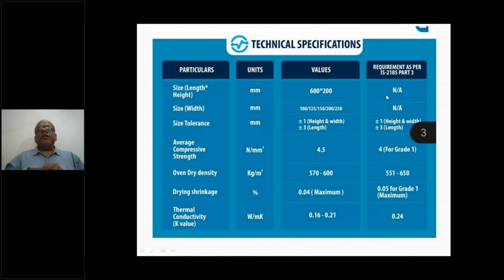So we always request, wherever we advise, I advise to clients that don't use AAC blocks if you get them hot on your side. If the AAC block is hot on your side, this means the plant has dispatched them quickly. It happens, customer is shouting, his labor force is sitting, so the plant will dispatch. But if you don't want to have any cracking issue in your wall, leave them for 48 hours, let the humidity come to equilibrium with your atmosphere, and after 48 hours you put them inside your wall. So that is about our dry density.